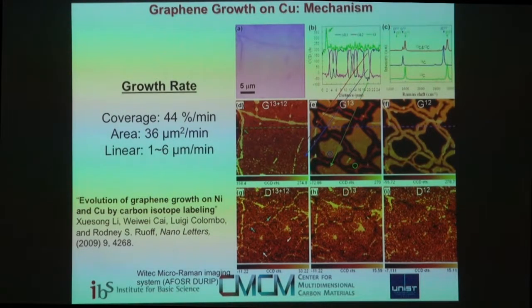So if you look at what you get here, you have regions that are pure C13 graphene, and then regions that are normal graphene, and then in the third minute, the islands stitched together, and the surface was coated, and so the catalytic activity stopped, and it stopped at a monolayer. If I were showing you the image from nickel, it would look like one uniform color because isotopic scrambling happens subsurface by diffusion, and what's on the surface when you take the sample out at room temperature is a consequence of precipitation. But in this case, this proved that in the first minute, nucleation had occurred, and then island growth, and then in the second minute, it grew further, and finally in the 3rd minute, it finished growth.